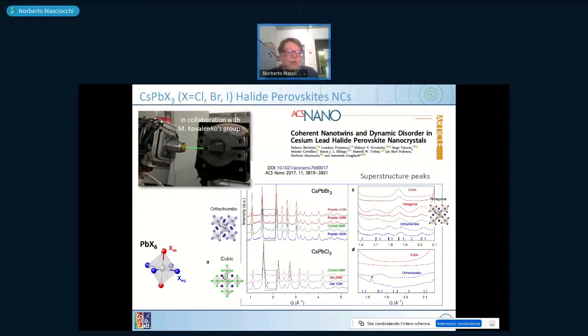So to make the story short, the perovskites are based on this kind of lead halide octahedron. And the lead halide octahedron is normally described by 2 axial and 4 equatorial halides, because only in the cubic phase, which happens to occur only at high temperature, all the 6 atoms are equal. If you go down to what is called the tetragonal or orthorhombic phases, which are obtained on cooling, there is some distortion, and then you have a clear distinction of these different halides. So our measurements were done at different temperatures. You can see, read here from 450 down to 133 in different conditions, in a colloid, as powders, or even in gel.